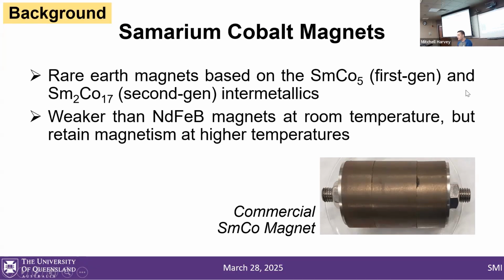So above about 150 Celsius, samarium cobalt outperforms neodymium iron boron. And so it sees a lot of use in very specific high technology applications, such as radar receivers, certain motors, and control surface actuators in airplanes.